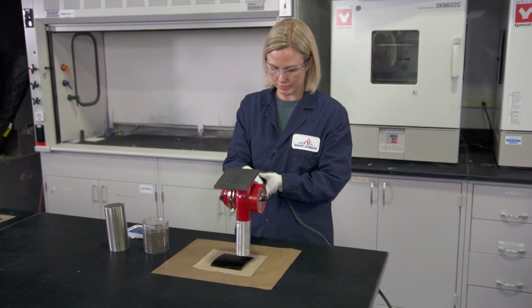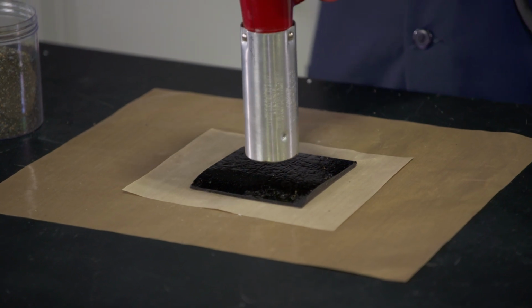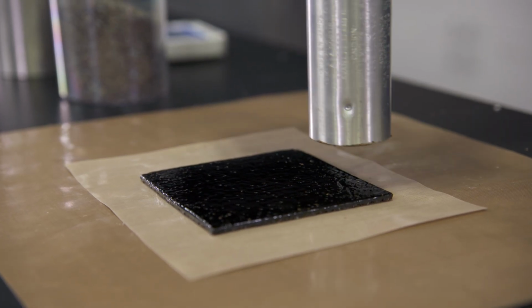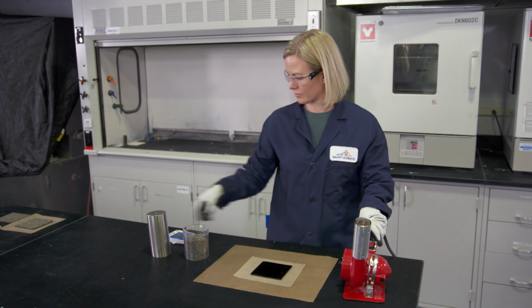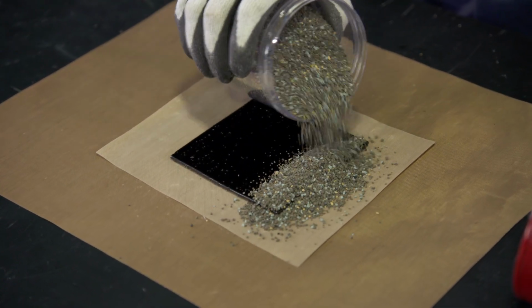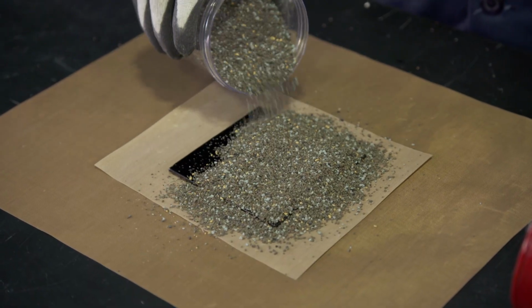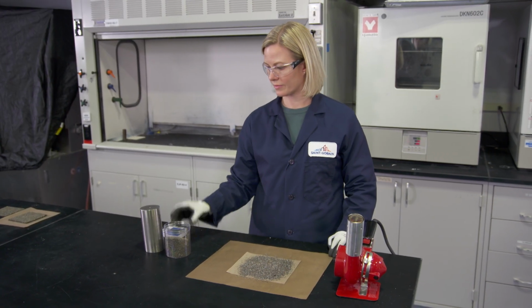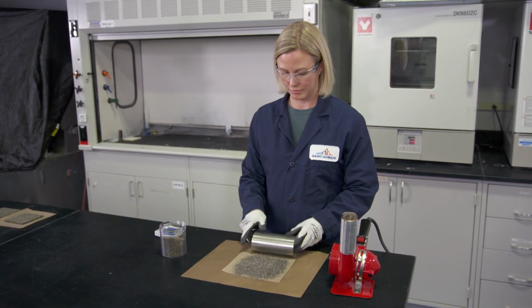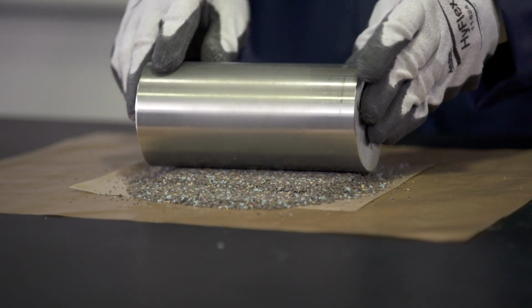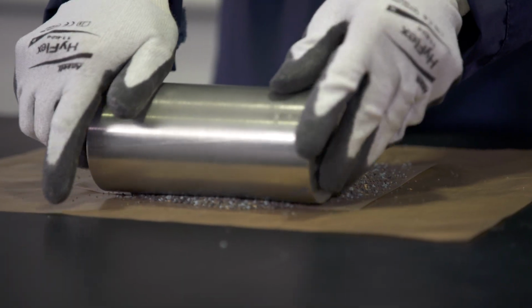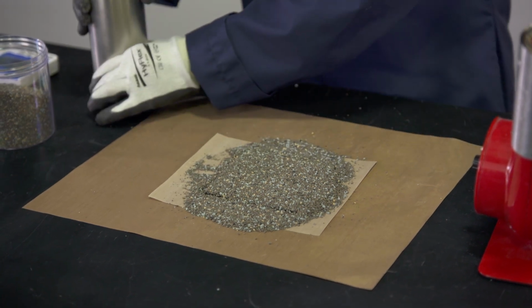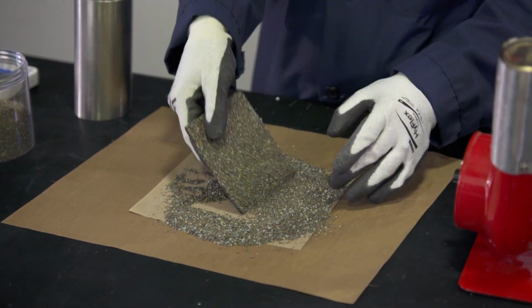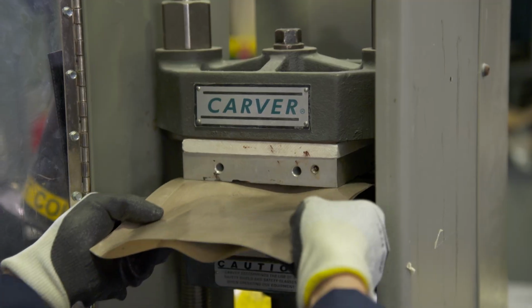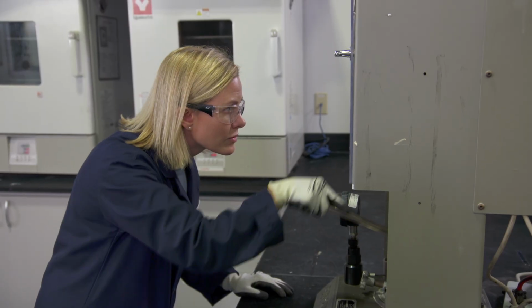So Jenn will use the heat gun to heat the asphalt in order to accept the granules hot. And we do this under a timer in order to get the right heating profile on the asphalt substrate. How long is that? It's about 48 seconds. Jenn will then take the granules and pour them onto the top of the asphalt substrate just to coat it. And then she'll use a weighted roller to roll the granules into the asphalt substrate. Jenn will then shake off the excess granules, and then we put this into a press and press it hot under pressure for about a minute to ensure the granules are embedded in the asphalt substrate. It's pretty precise. Yes.